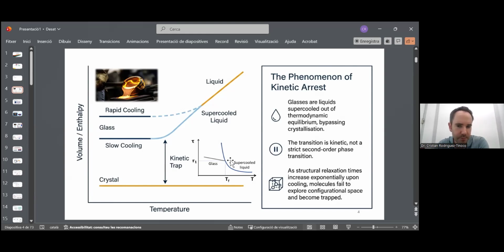When we enter the supercooled liquid regime, in this plot you can see that the relaxation time increases very sharply when reducing the temperature. Eventually, the time the system needs to equilibrate to stay in the supercooled liquid state is longer than the available experimental time. So at this moment, the system goes out of equilibrium, and then we form a glass. If we go faster, this deviation from equilibrium occurs at higher temperature. If we go slower, we can stay at equilibrium down to lower temperatures. But this range of temperatures at which we can stay in equilibrium by cooling at different rates is significant.